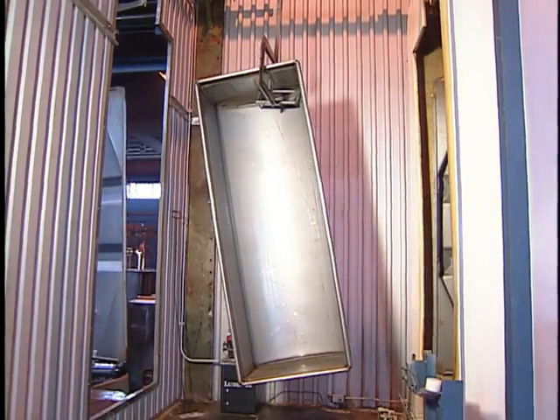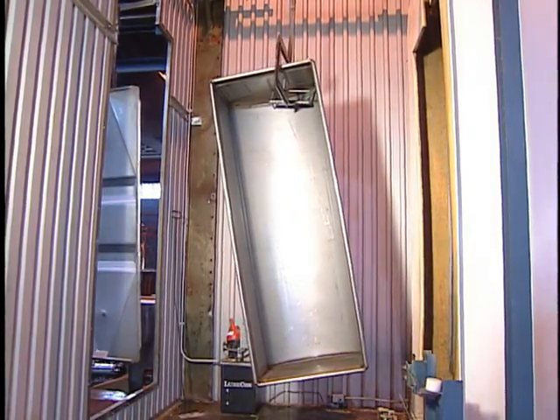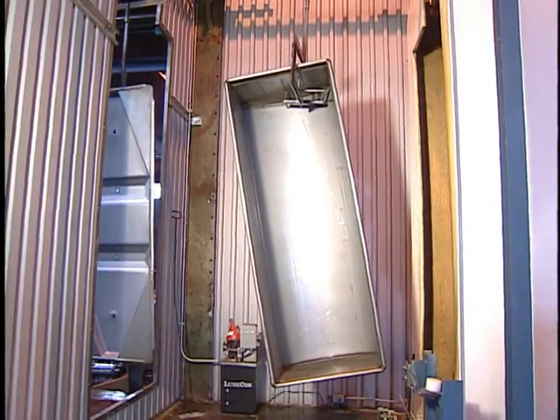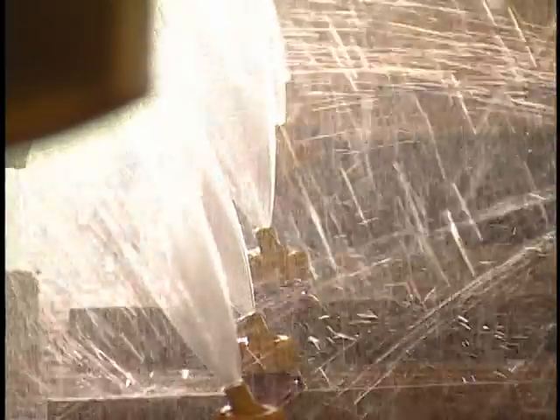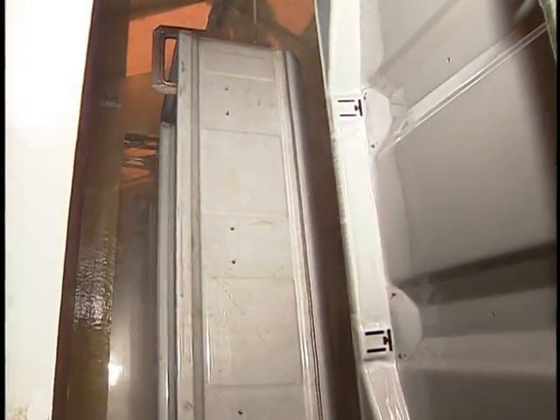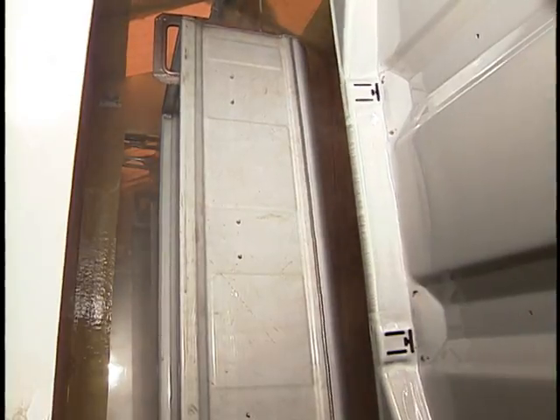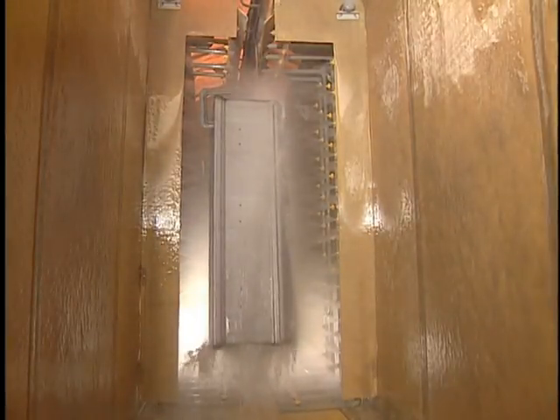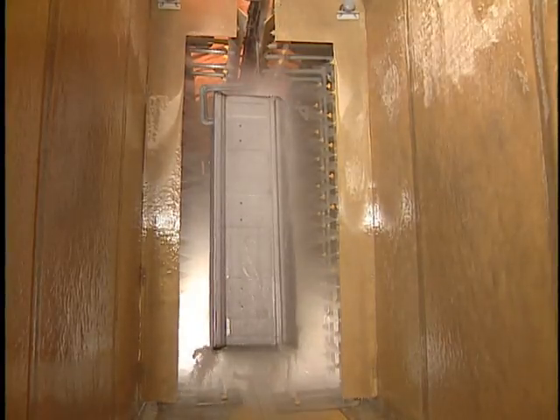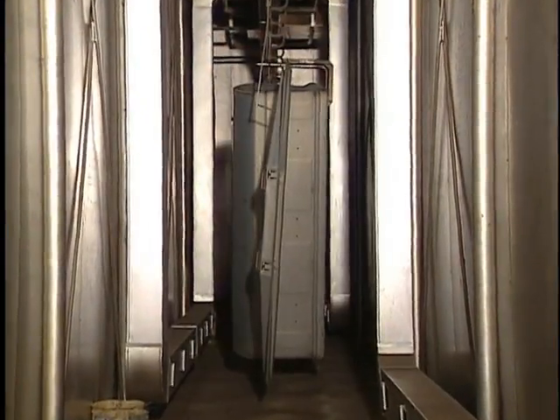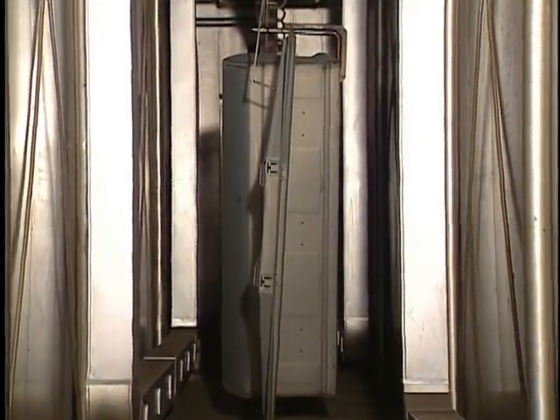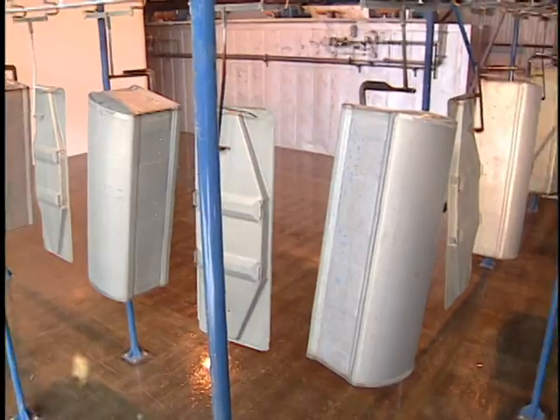Prior to powder coating, the dome, base, and handles are exposed to a 20-minute, 5-step wash and surface preparation. First, a 90-second wash in alkaline removes oil and surface dirt, followed by a water rinse. Then, an iron phosphate coating is applied to etch the metal, giving the powder a rough surface on which to adhere. After another water rinse removes excess phosphate, a special chrome-free rinse cleans the surface of contaminants and prevents flash or immediate rusting. The parts are then dried in an oven heated to 250 degrees Fahrenheit and cooled prior to powder application.